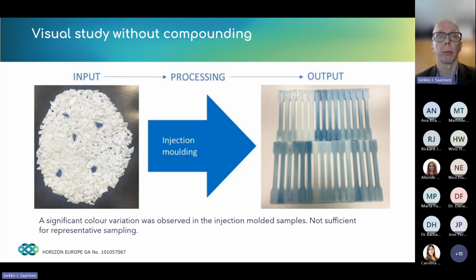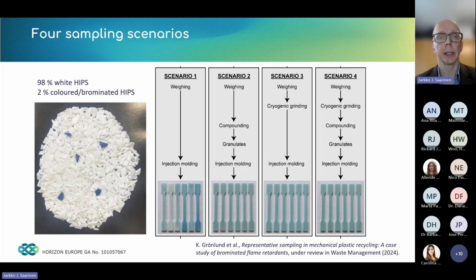Some of the dog bones are more or less intact, whereas some of the dog bones that have just been injection molded are showing a significant density of the blue color. So we can clearly see that this is not a sufficient manner of doing representative sampling of the streams. So then we have studied the 4 different scenarios, with the same mixing ratios, and here is an example of the image that is also included in